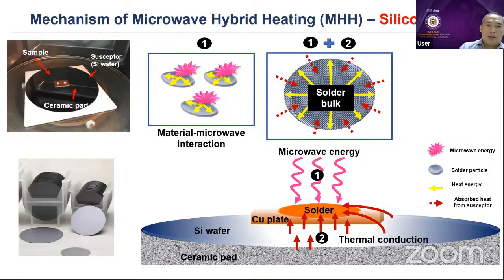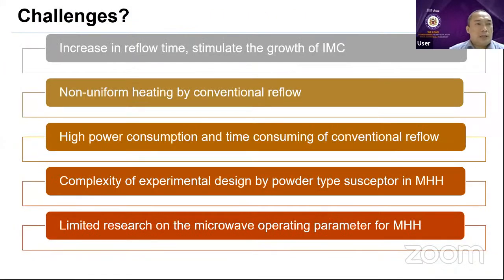Okay, so these are the challenges when we do this kind of research, means that dealing with the microwave, and then the increase in the reflow time stimulate the growth of IMC. We don't know that how fast or how thick the IMC will form. And then sometimes the non-uniform heating by conventional reflow, that can be overcome or not. The high power consumption by the reflow, hopefully we can cover by this microwave.